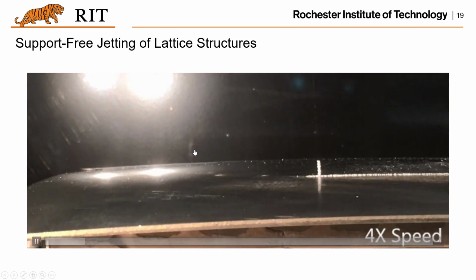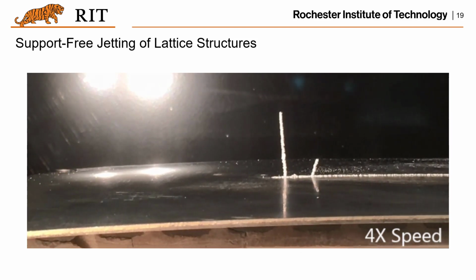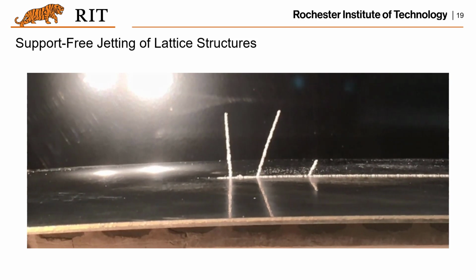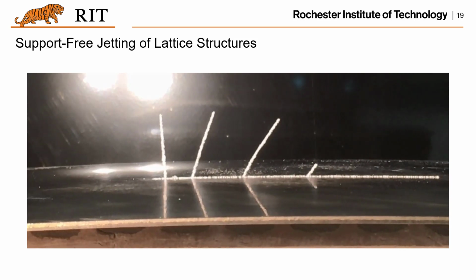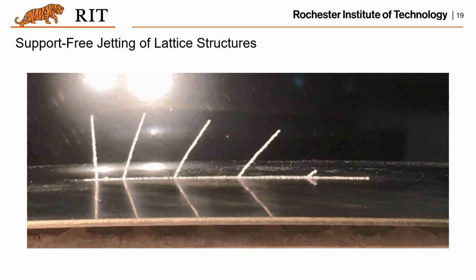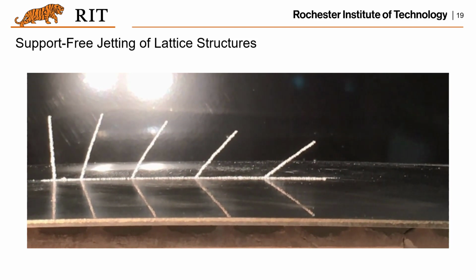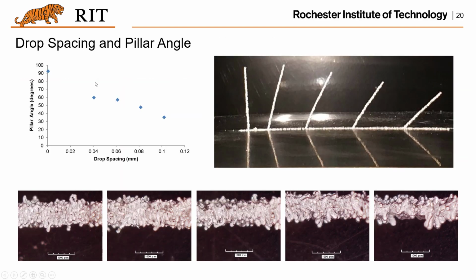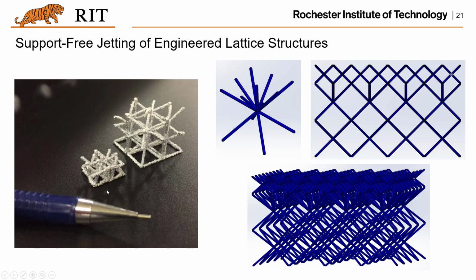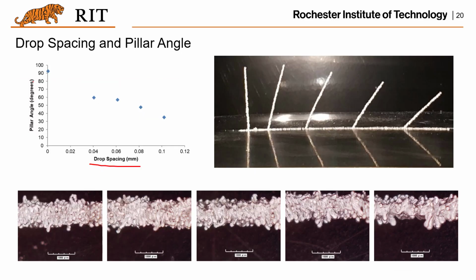So it is possible for this printing process to print lattice structures without support material. You can see the angle becomes larger and larger, and it turns out it does not require any support. As you can see here, it shows a relationship between the drop spacing and the pillar angles. When the angle decreases, the drop spacing increases, and it turns out it's roughly on the same straight line, which is a very good property. And that's how this kind of printing without any support is possible.